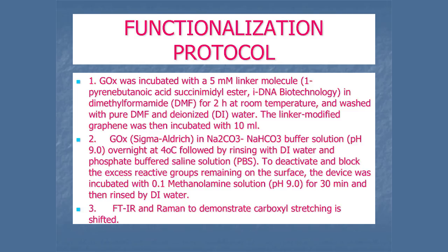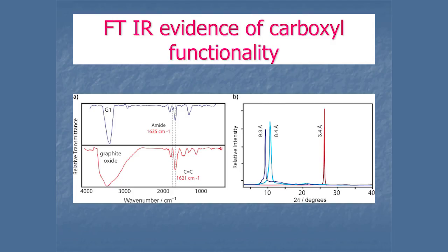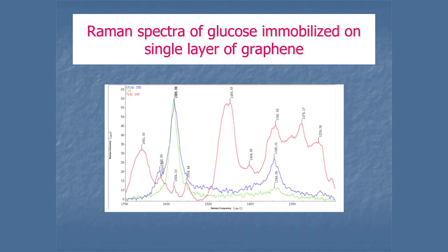The linker-modified graphene was then incubated with 10 milliliters of the rest of the buffers, and we used Fourier transform infrared. You can see the infrared here. You can see a shift in the carbonyl stretching region, indicating that the covalently attached protein or enzyme is really bound to the graphene single layer surface. We also use Raman. Raman is more conclusive. With Raman and infrared, we have evidence that the functionalization has gone through and the proteins are attached and quite intact.